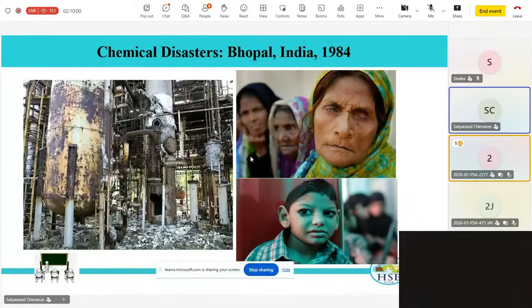But the problem was not methylamine. The problem was methyl isocyanate only. When water unfortunately got dripped into the reactor and methyl isocyanate started reacting with water, heat liberation resulted in methyl isocyanate releasing from the storage unit. And we are talking about 40 tons of methyl isocyanate being there, and then nearly 25 tons of methyl isocyanate spreading across and across the whole of Bhopal city.